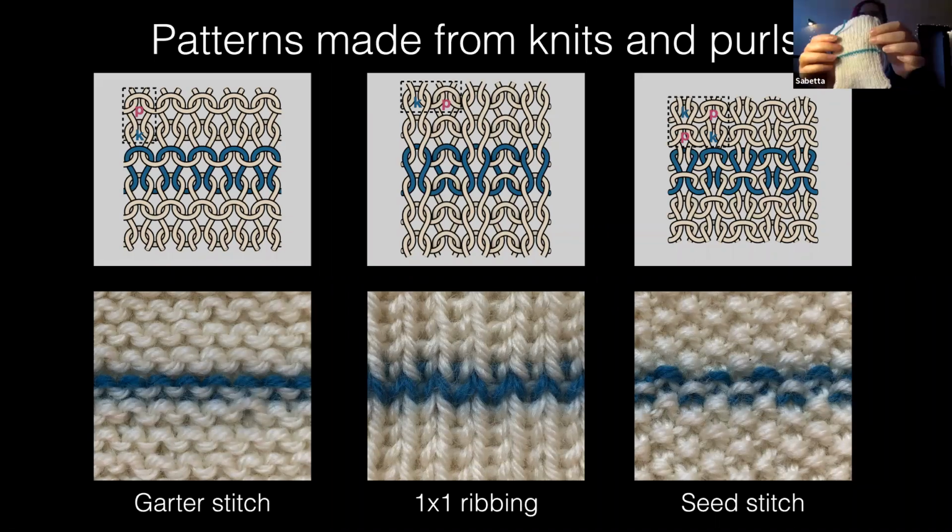The rib stitch is incredibly stretchy in the horizontal direction. So this is used in places like cuffs and collars, places where you really want to have additional elasticity to your garment. It turns out that it's not very stretchy vertically, and this comes a bit from the fact that the columns are getting jammed together, but we haven't quite included that in our model yet.